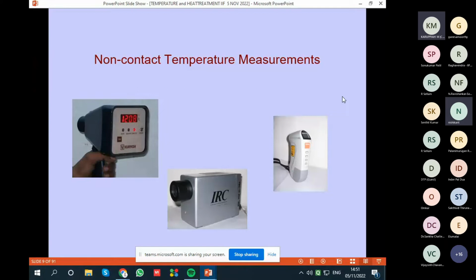There are various models available. During corona days, you know that your temperature was measured by the small instrument on the right-hand side. Your body temperature, say 98 or 97 degrees. And there is one in the middle, which has many facilities like giving an output connected to a data logger, etc. This you can mount in the plant and measure the temperature. But if you want to measure the molten metal temperature, then the instrument on the left-hand side, which is handheld, is very easy to use and gives you a quick temperature measurement in about 2 to 3 seconds.